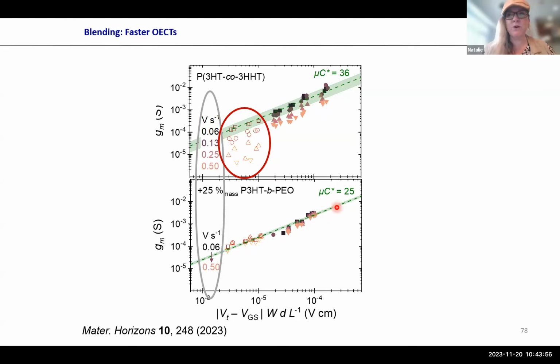Versus once you blend, and I really think that's important if you want to go further in engineering eventually, the devices scale extremely well, actually nearly too well for my taste, but it shows the blending makes the devices super well behaved, and it doesn't matter whether you have small or large devices. What you see here, and that's a bit the problem with only going with polyethylene oxide, you lose a bit in that key parameter of organic electrochemical transistors, which is the product of mobility and capacitance. But I think it's still pretty good. And I'm sure with clever design of this block copolymer, this was at the end pretty random, actually, that we picked that one, we could get this mobility-capacitance feature up.